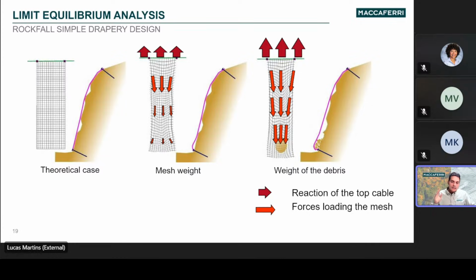It's overlooked because the model assumes that under load, the top horizontal cable is uniformly loaded and the wire mesh is uniformly tensioned. But in reality, the mesh undergoes a non-uniform deformation as it adapts to the slope geometry and transfers the load. Rather than transferring the load evenly, a mesh with a large elongation will create pockets of concentrated tensile force, which can be especially damaging when debris accumulates at the bottom.